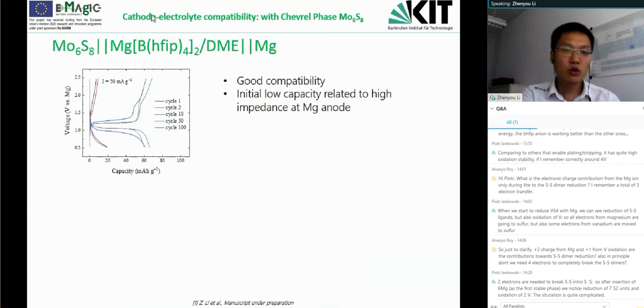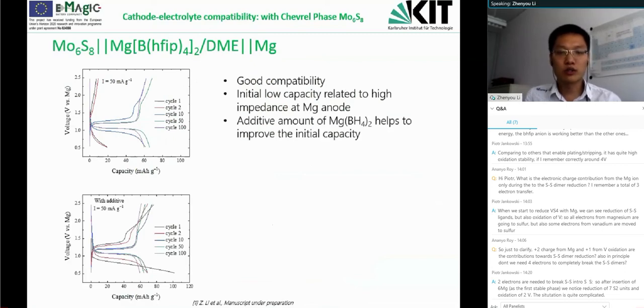The initial low capacity is related to the activation process at the magnesium side. So we also observe a similar phenomenon or activation process in the magnesium symmetric cell by using this borate electrolyte. And here, in order to deal with this problem, we also try to introduce an additive amount of magnesium borohydride to the system, just hoping that it could somehow clean the magnesium surface. And the cell indeed shows a good capacity and also distinct voltage plateaus, even in the first cycle and onwards. So this means it works.